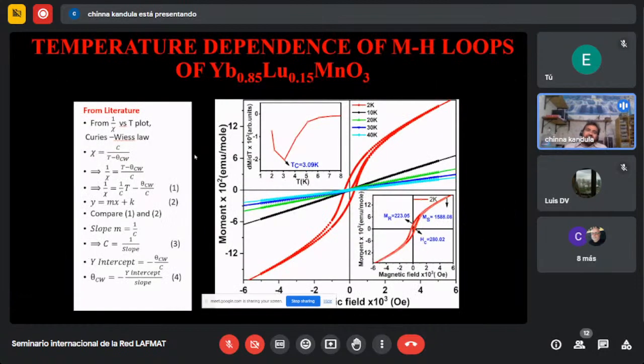Next, I want to see how the material behaves, so I take the MH loop, the MH measurements, for my samples. From the MT data at low temperature, the Curie constant and the Curie temperature are calculated. The Curie temperature at low temperature comes around 3.09 Kelvin. These samples are generally paramagnetic at room temperature, but at very low temperature like 2 Kelvin, the magnetic phase changes. You can see the trend here.